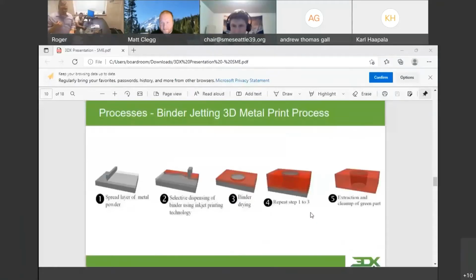But so we coat that layer by layer, and then we have a precision print head that has 1,100 print jet nozzles that are controlled by little piezos. You guys probably know that better than I do. It's the engineering side. They're little valves that so accurately deposit the binding agent. Then we spread a layer of metal powder about 3 thousandths thick. Then we bind that together, and you continue on until you've done the whole box. You continue to repeat the steps until you go the whole 10 inches on the print box.